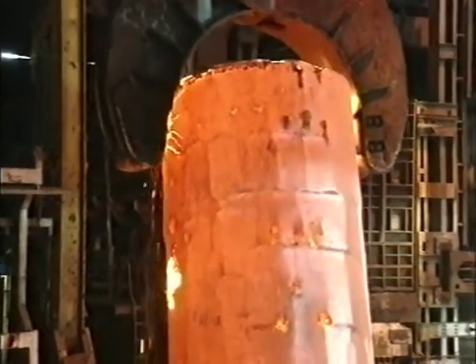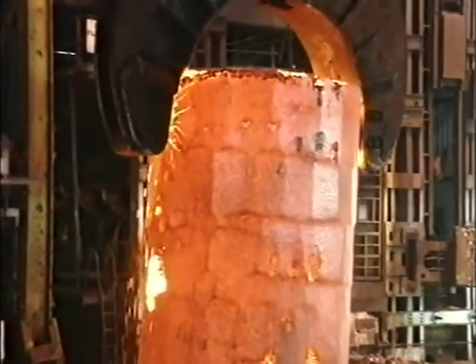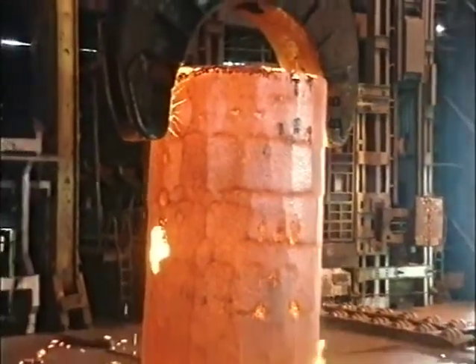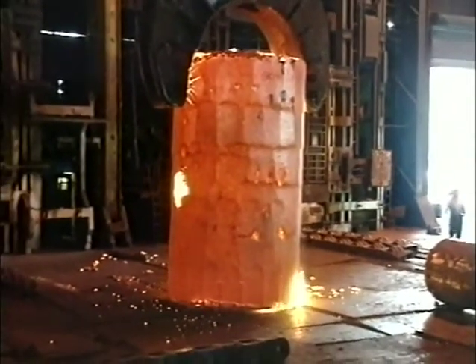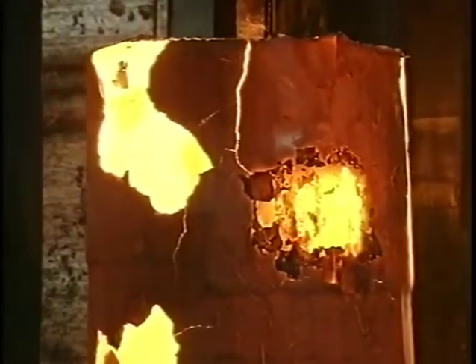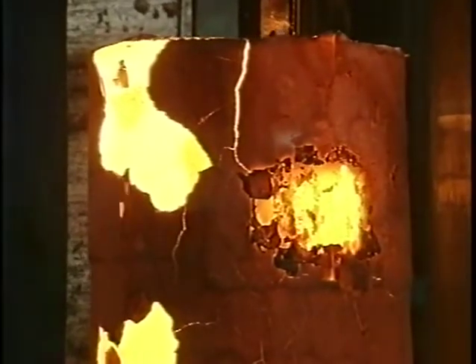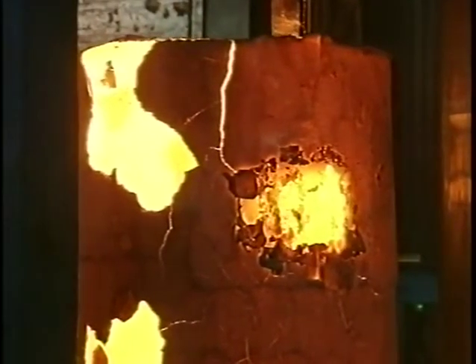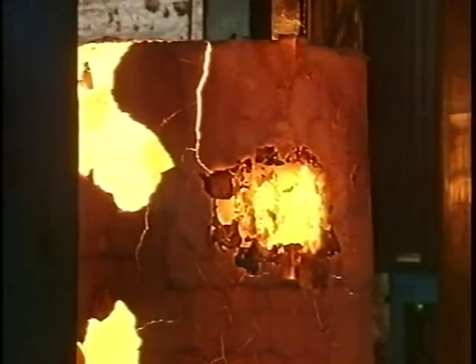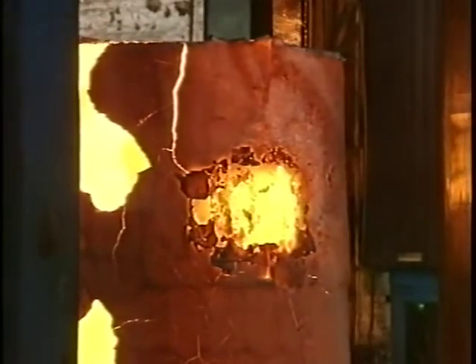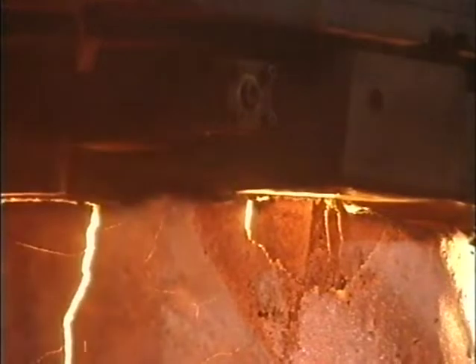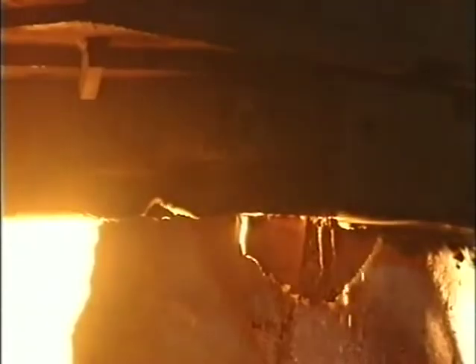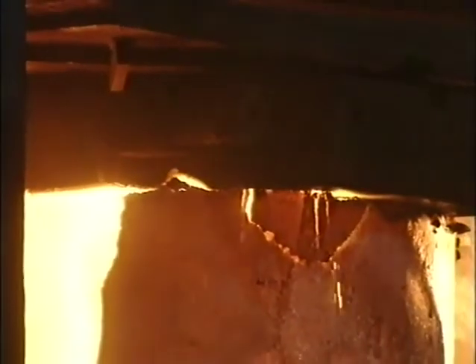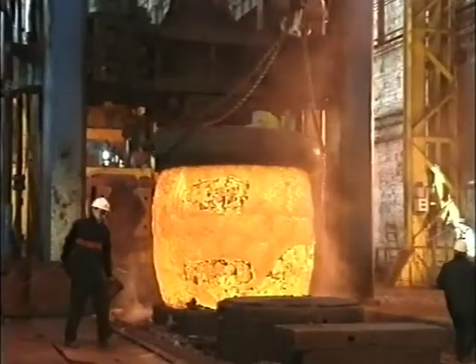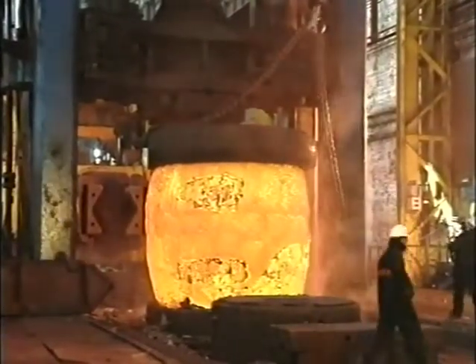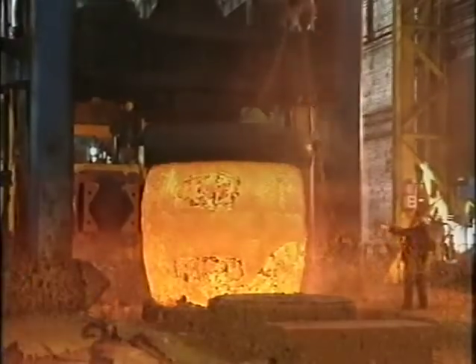This steel bloom weighs over 150 tons and has been heated and soaked at a temperature of approximately 1250 degrees centigrade. The importance of temperature control cannot be overemphasized. Too high a temperature may result in melting of grain boundaries in the bloom. Too low a temperature may result in cracking or bursting of the bloom during forging.